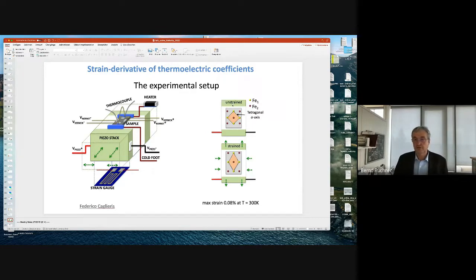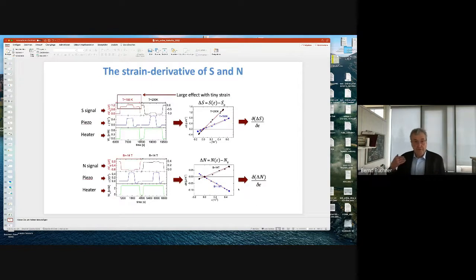And this you can do in a strained system and in unstrained systems, and from the difference, which is tiny, you can then derive the derivatives again. And the real first surprise is that there are really very clear changes upon tiny strain. So this is a typical experiment. So you switch on the heater, you have the thermopower here, you switch on the piezo, you strain the sample, you see a change here, goes back when you switch off the piezo again, and then the signal disappears when you switch off the heater.